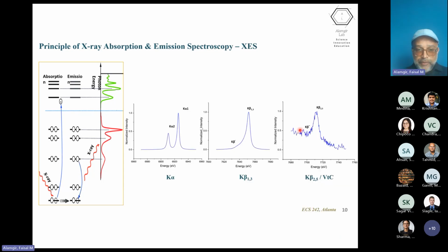X-ray emission, I've described what it is before, but even though it describes the energy level difference between two electronic levels, which are well defined, and that difference should essentially shift in tandem with each other when the chemistry of the atom changes. The very fact that there are different energy levels means that the outer electrons and the deeper core electrons don't shift the same amount due to the different levels of screening that they have to the different charges involved. And so what that means is that even though they move in tandem, that slight difference between that movement is enough for us to pick up chemical state information. That is a slight information difference.